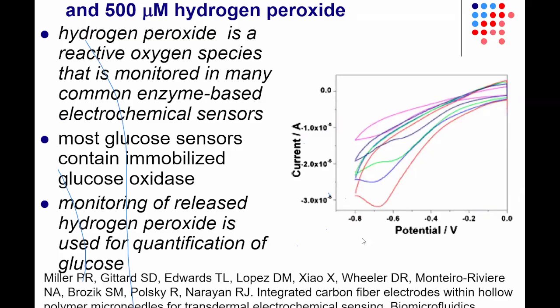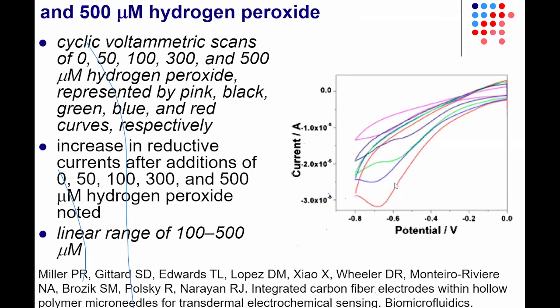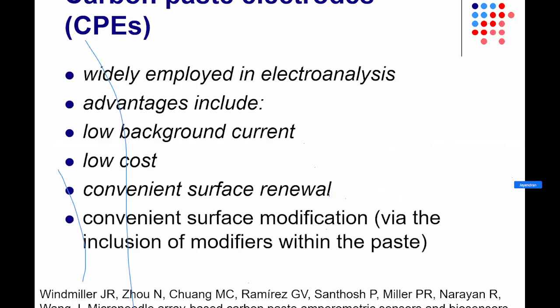Here you can see this idea of using this sort of device for hydrogen peroxide sensing. Of course, hydrogen peroxide can be coupled with a variety of different enzymes so that you can detect biological molecules. And here you can see that you are able to get these sort of characteristic CV scans for concentrations of 0, 50, 100, 300, and 500 micromolar hydrogen peroxide. So we have a linear range for the output between 100 and 500 micromolar levels.